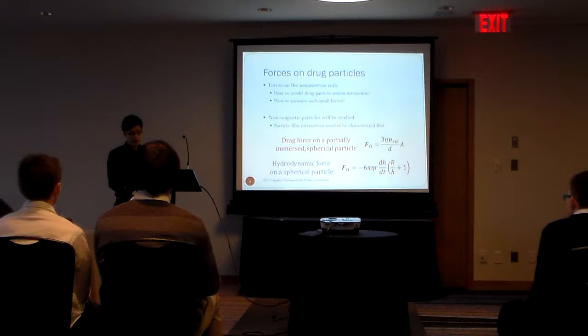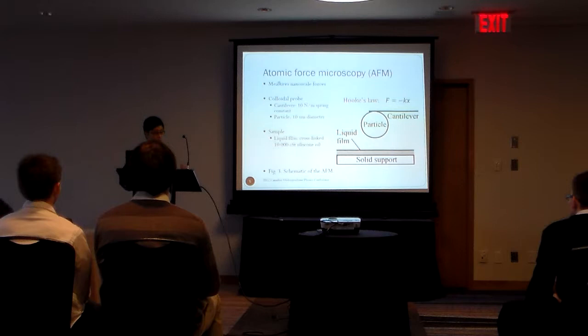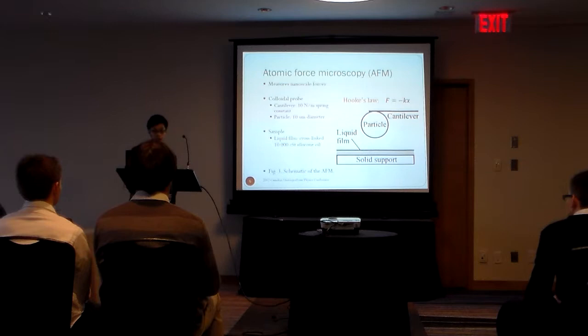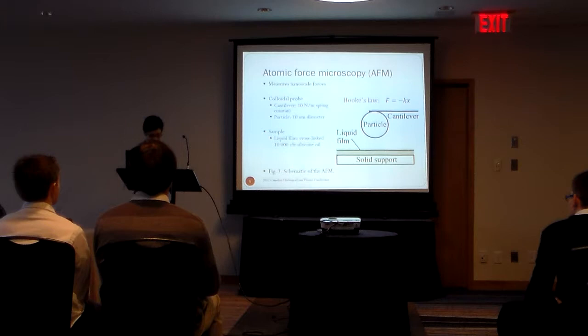The nano-Newton drag and hydrodynamic forces can actually be measured using atomic force microscopy. A particle made of either polystyrene or silica can be attached to the end of a cantilever, which has a known spring constant. This entire structure, known as the colloidal probe, will approach and retract from the sample — a cross-linked liquid film with similar non-Newtonian properties to mucus.